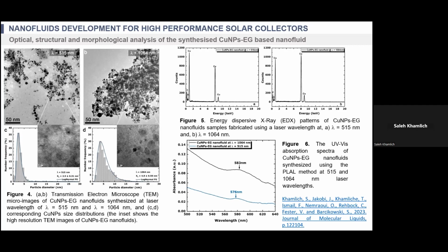What we found, by using the 515 nanometer laser, is that we managed to produce smaller nanoparticles in the range of 2.5 nanometer. This is a particle size distribution here. This is the statistics coming from these particles. We measured the size of each and every particle, and we came up with this histogram. It gives us an average size of around 2.5 nanometer with an error of 0.31 nanometer. Using a laser of 1064 nanometer, we found that the produced nanoparticles are a little bigger, in the range of, let's say, 4.8 nanometer with an error of 0.15 nanometer.